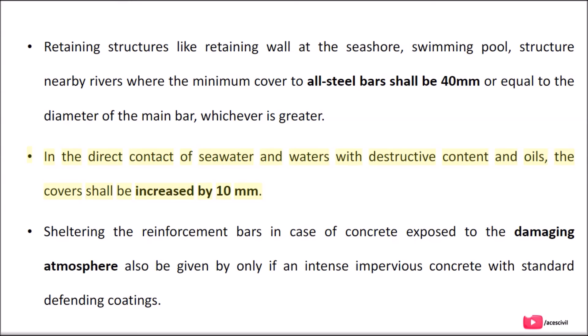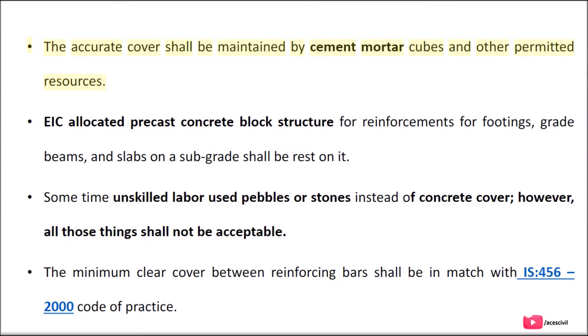In direct contact with seawater and waters with destructive content and oils, the covers shall be increased by 10 mm. Sheltering the reinforcement bars when concrete is exposed to a damaging atmosphere can also be achieved by using an intense impervious concrete with standard protective coatings. The accurate cover shall be maintained by cement mortar cubes and other permitted resources.